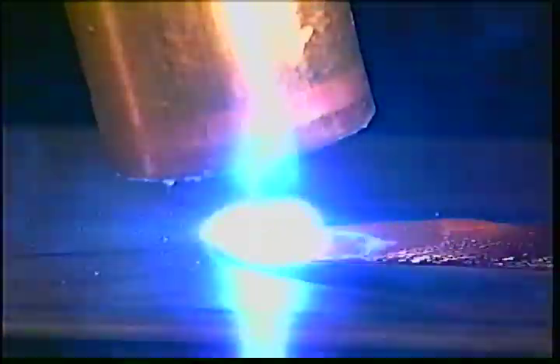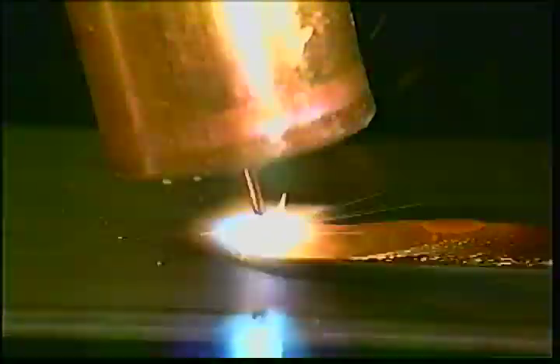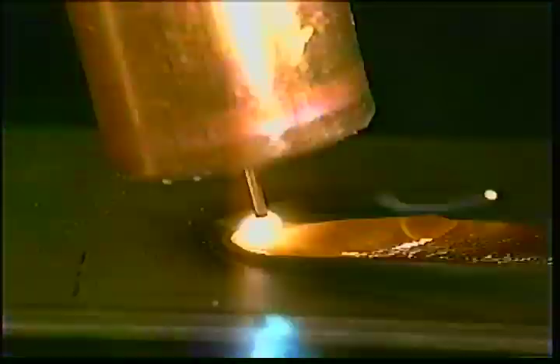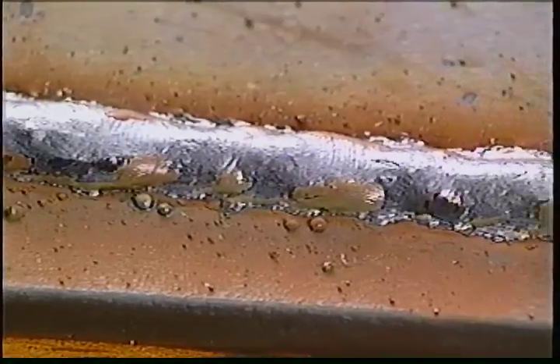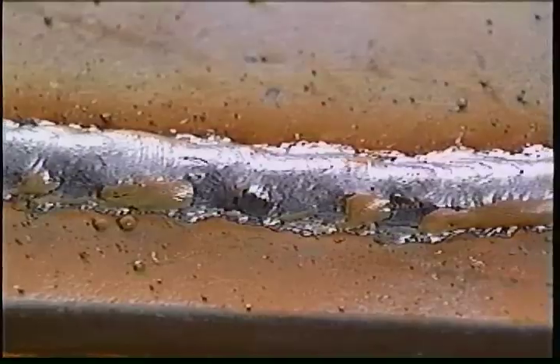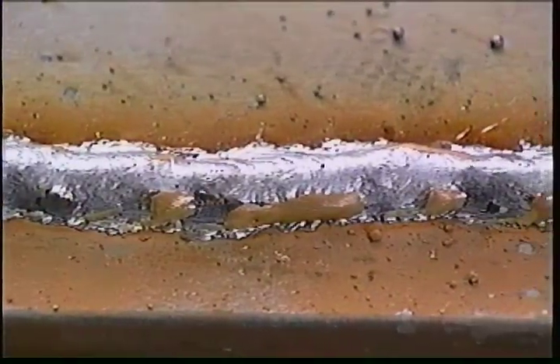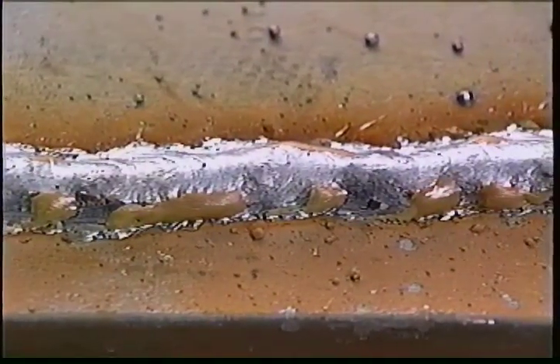These short circuits occur at a rate of 20 to 250 per second, depending on wire feed speed. With short circuit transfer, wire feed speeds, voltages, and deposition rates are usually lower than other transfer methods. Small diameter electrode wire is used, and the weld pool cools between each short circuit, allowing the process to be used for out-of-position welding. Production of some spatter and a potential lack of fusion on thicker materials are 2 limiting factors with short circuit transfer.